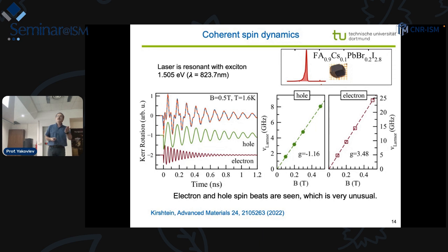And this is exactly the specifics of the perovskite semiconductors, that we have electrons and holes sitting in the same material in different places. We polarize them, and then we can observe their spin precession. And the times we observe them go beyond 2 nanoseconds, so much beyond the exciton recombination time. These are really resident carriers. We can plot the frequency of the precession as a function of magnetic field and evaluate the g-factors. The g-factor is 1.1 for holes, 3.5 for the electrons.